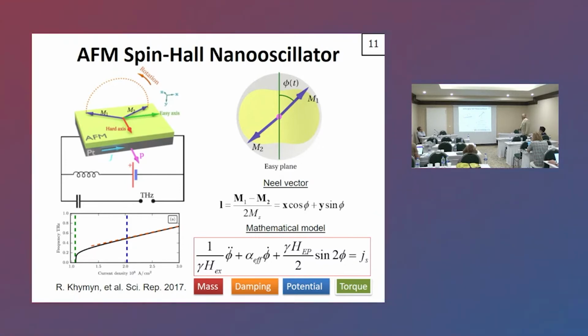And the equation which describes this is very similar to the equation describing the oscillations in the Josephson junction, where one over the exchange field plays the role of the effective mass, the effective damping is the usual Gilbert damping, and the Josephson potential is replaced by the potential where phi is the azimuthal angle of rotation of the sublattices. And the frequency, as you see, can be about half a terahertz when the current density is about 10 to the 8 ampere per square centimeter. And we have here a big specialist in spin torque oscillators as our chair, and he knows that in principle you can reach these current densities in real experiments.